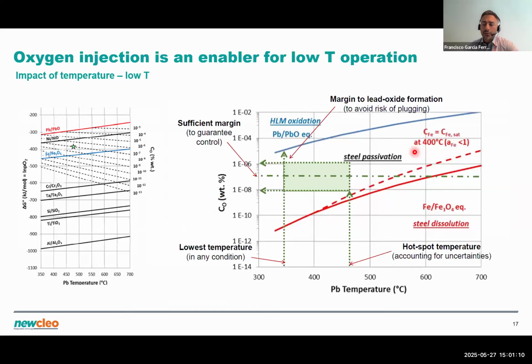rates. Now, if you look a little bit more into the details, you can define some stability regions for the oxides that are formed when steels enter in contact with oxygen. For example, the red line here is displaying the stability line for iron oxides, and the blue line is displaying the stability line for a lead oxide. So if we inject a certain concentration of oxygen into our system, we want this concentration to stay below the stability line of lead oxide because we don't want to form lead oxide, to avoid plugging our system, but we also want to stay above the stability line of iron oxide because we want to form these protective oxides.